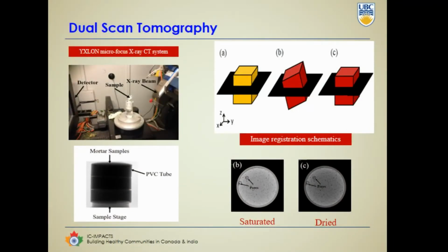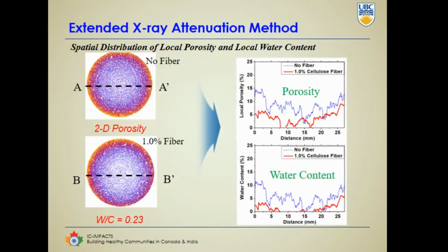Now through some tomography scans here, we're looking at these dual scan tomographies with Xylon. And you will notice that when you look at systems which have cellulose in them, here's the tomography scan without cellulose, and here is the one with cellulose. You can see that I'm also reducing the total porosity, and at the same time, I'm also reducing the water absorption, which means that with a small amount of fibrillation, this system is becoming a lot more impermeable, reducing the porosity and increasing the strength at the same time.